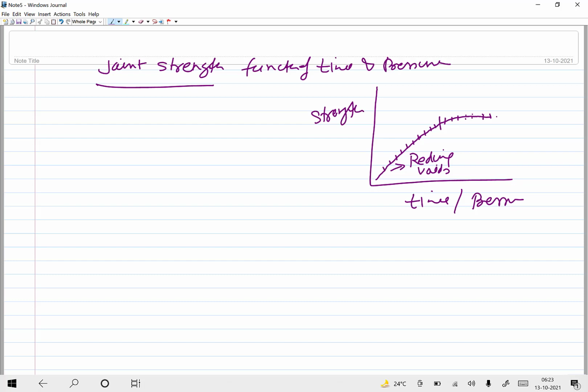The same is true for recrystallization also. Whatever recrystallization has to happen will be completed in a certain period of time during the diffusion bonding, and thereafter no further change in the microstructure in terms of recrystallization will take place. Actually, the diffusion bonding time varies significantly. It can change from a few minutes to a few hours. You may get a diffusion bond in 5 minutes, or it may take 3 to 4 hours. It depends on a number of parameters.